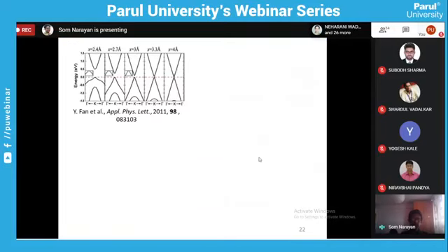The motivation behind that in the master's was that at that time graphene was very popular, so we doped it with different doping, with nitrogen, and there is a band opening. It shows the layer interaction between hexagonal boron nitride and graphene. As we increase the distance between the hexagonal boron nitride and the graphene, there is a band gap at nearly 2.4 angstrom. The band opening is there, but as we move to 4 angstrom, there is no interaction between the hexagonal boron nitride and graphene, so we have the semi-metal nature again.